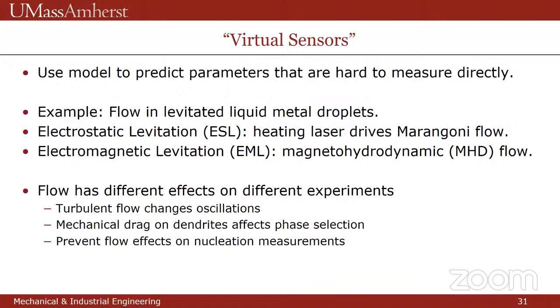So virtual sensors. This is the next topic. The idea is to use the model to predict parameters that are hard to measure directly. So for our fluid flow in liquid metal droplets, it's driven by either Marangoni convection or magnetohydrodynamic flow. And we have different reasons for different experiments that we need to quantify different things about the flow. There are a lot of experiments that set the droplets oscillating to measure properties like viscosity and surface tension. There are other experiments where we showed that mechanical drag from the fluid flow can affect the phase selection, the nucleation of a second phase during solidification. And then the last one that I'm going to show you, on one slide or two slides today, is how the fluid flow affects the concentration field around growing nuclei.